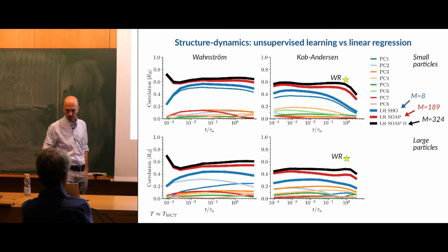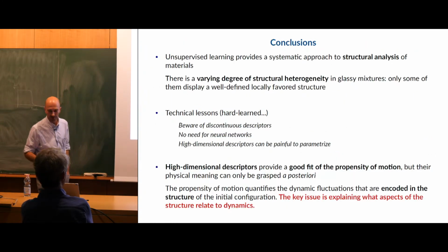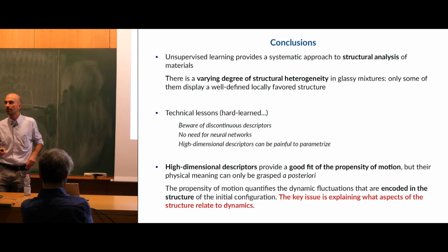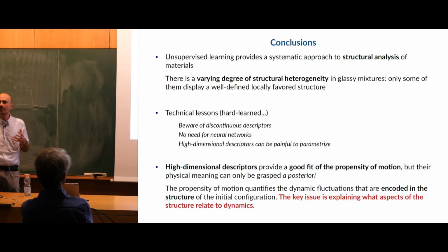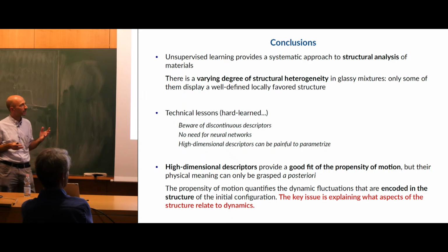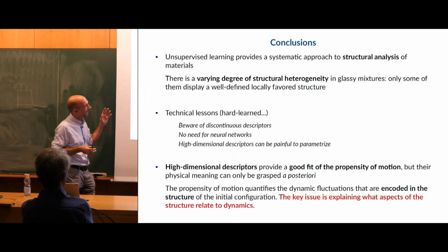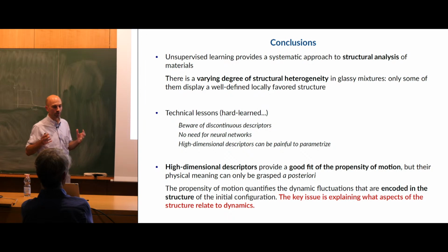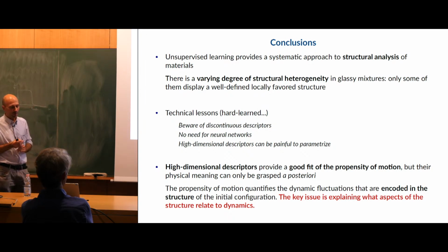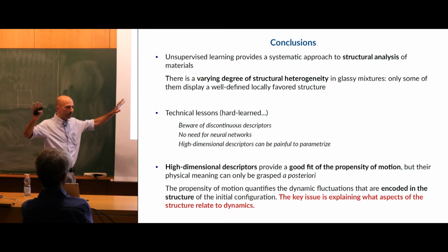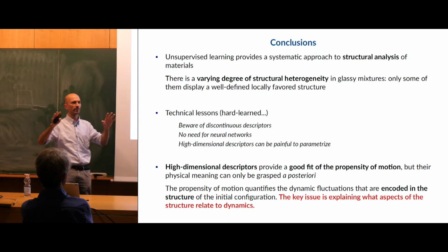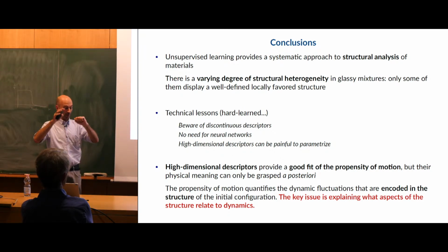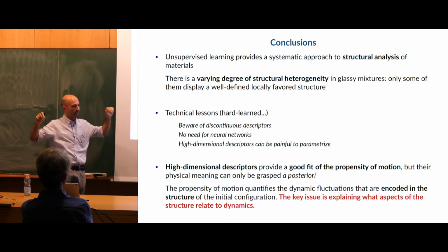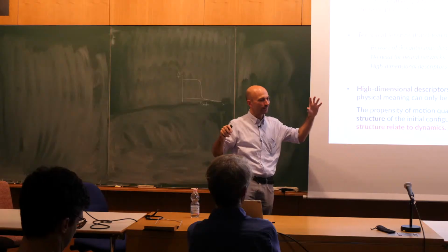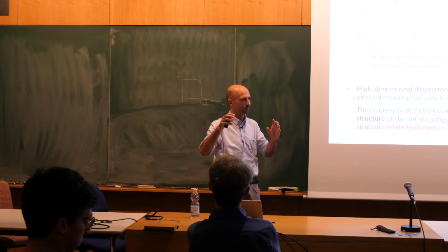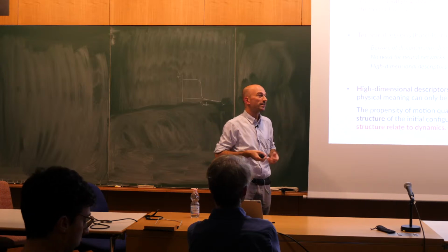All right, so I think that's almost all. I think my conclusion is that unsupervised learning is a promising route to look at structure in amorphous materials and to provide a robust definition of locally favored structures. And one thing that we see, at least around the mode coupling crossover, is that there is a varying degree of structure heterogeneity in the models that we have studied. There are systems which have a well-defined locally favored structure which stands out from the bulk, and others in which there is no such thing.